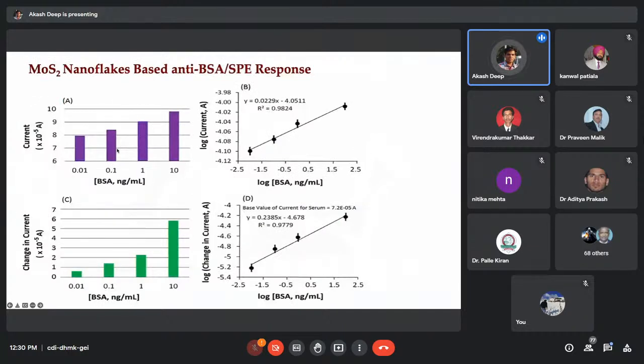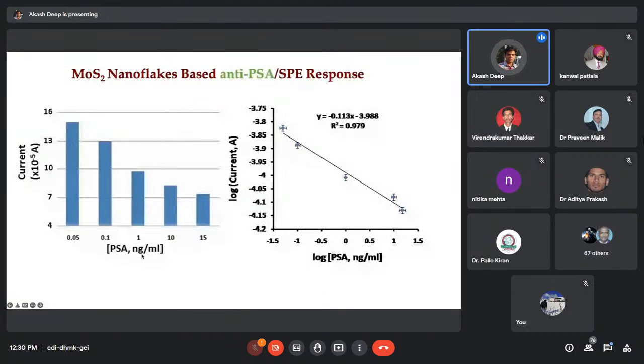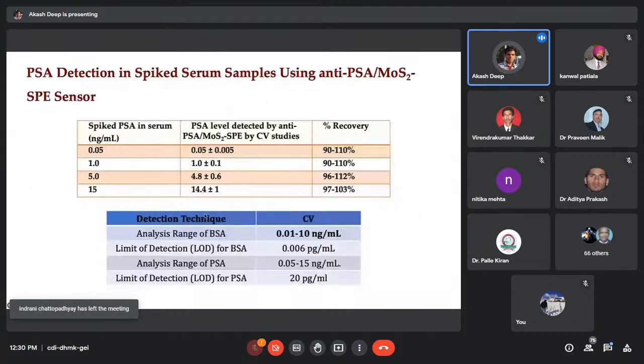This is the response of this sensor, how this sensor is responding to the presence of bovine serum albumin. You can see that with different concentrations, the current of this sensor is changing, and this is linear within 0.01 nanogram per milliliter to 10 nanogram per milliliter. So the sensitivity of this sensor is very good. And likewise, the sensor was also used for the detection of prostate specific antigen. We could detect the presence of this cancer marker to a very low level. And this type of sensor is also useful for the detection of these markers in serum, in blood samples. In blood samples also, we have tested them, and we found that the recovery, meaning the performance, is within the acceptable level.